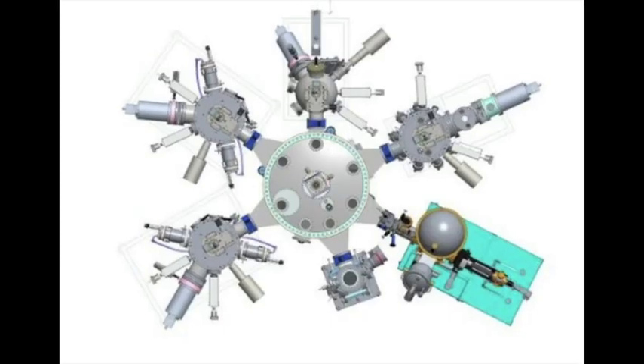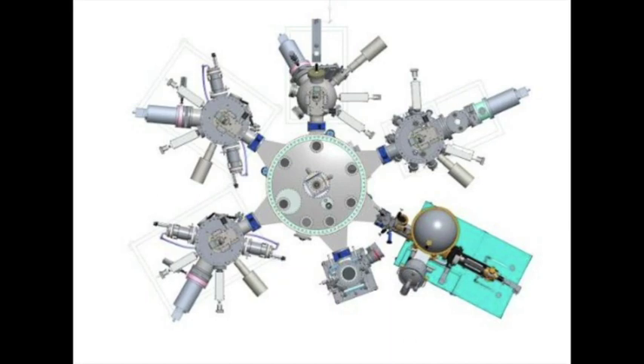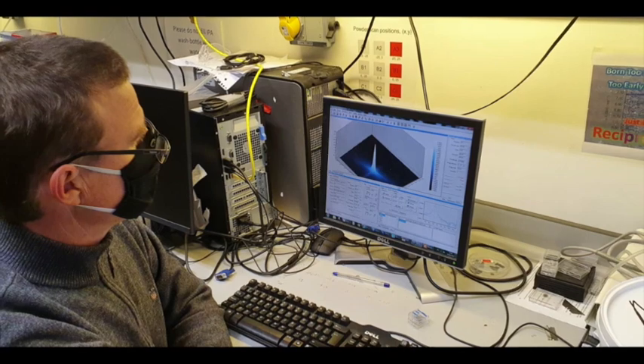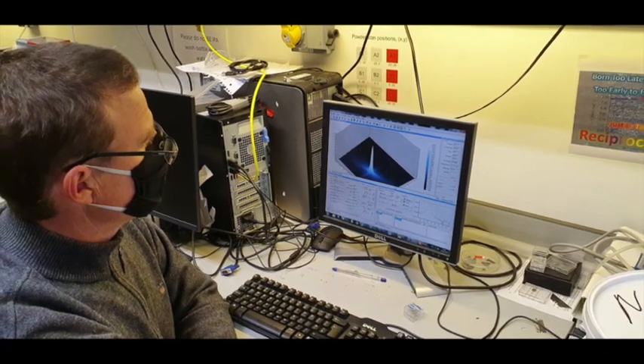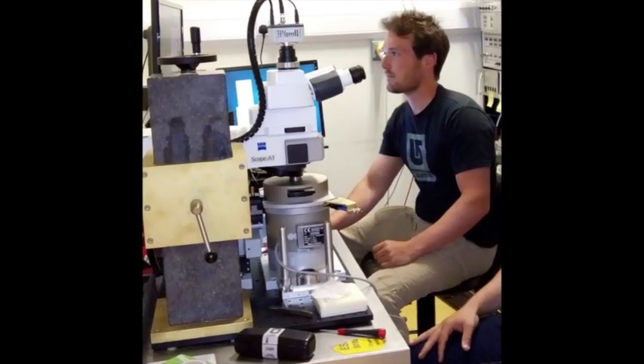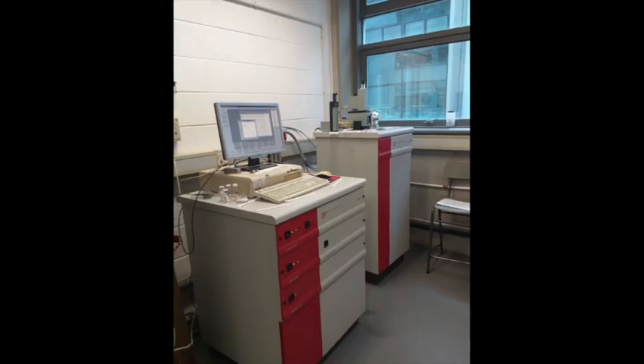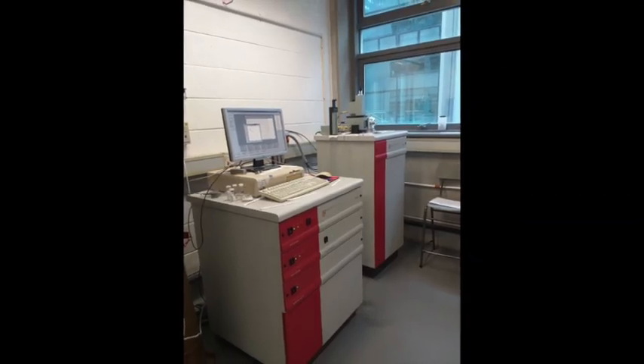And we're really lucky to have the new €3 million TEDdy facility, where we can make near-perfect devices by sputtering in ultra-high vacuum. The tool also includes chambers for in-situ study of the films just after we produce them. They must be thoroughly characterized by X-ray diffraction, microscopy to see if there are any magnetic domains, and then by SQUID magnetometry over in SNIAMS.